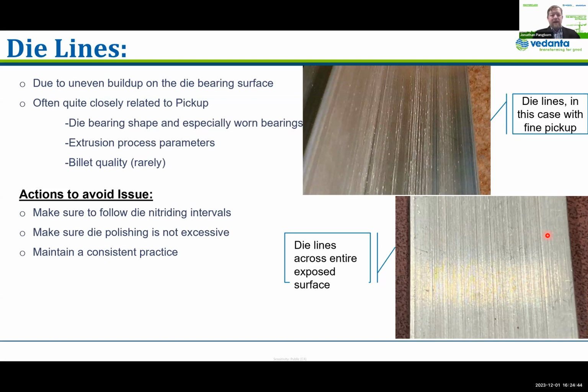This is again similar, but it's more related to the die bearing itself. As we're extruding, the aluminum is not actually sliding over the die bearing. There's actually an adhesive layer that forms, and these die lines are not necessarily a reflection of the die surface, but a reflection of that adhesive layer that is formed on the surface. So again, with rounded bearings, there can be a big effect: that adhesive layer may be unstable and inconsistent across, and we get die lines.